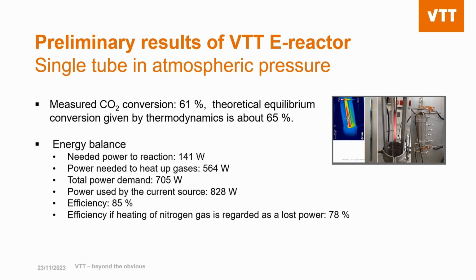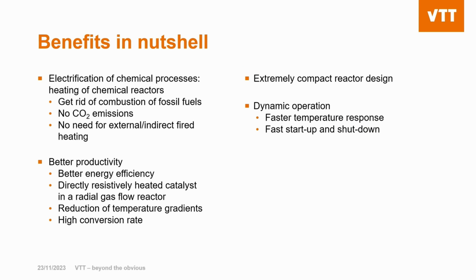So we started the testing, let's say, a couple of years ago, and these are the very first test results using a very simple reactor type, as you can see in the picture. But we could get quite high carbon dioxide conversion, where the measured value was 61% when the theoretical value at this temperature and pressure would be 65%. So it's quite a high value that we actually achieved here. And the efficiency was about 85% regarding the power usage. A little bit lower if we also take into account the heating up of this nitrogen carrier gas. But it looks very promising, and now we are currently making a little bit bigger reactor and using higher pressures to get better mass transfer values.